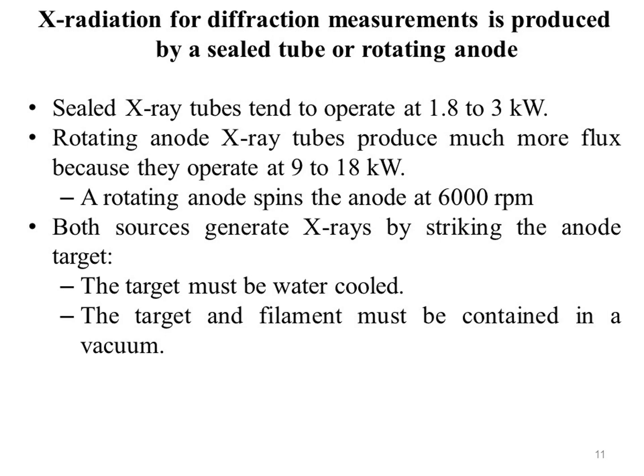kilowatt. A rotating anode spins the anode at 6000 rpm, helping to distribute heat over a larger area and therefore allowing the tube to be run at higher power without melting the target. Both sources generate X-rays by striking the anode target with an electron beam from a tungsten filament. The target must be water-cooled. The target and filament must be contained in a vacuum.